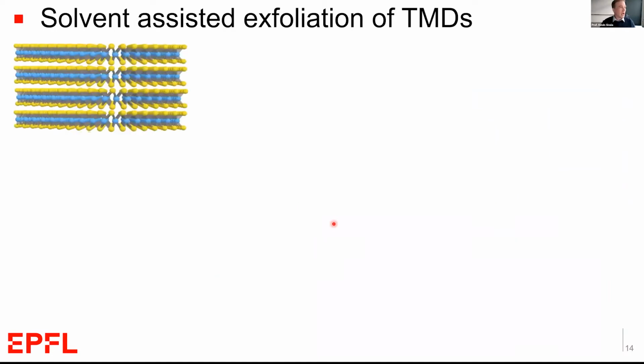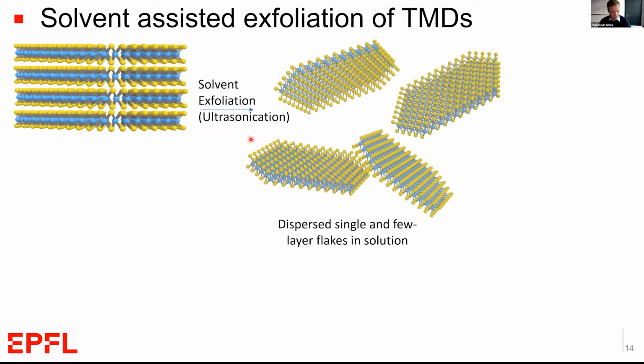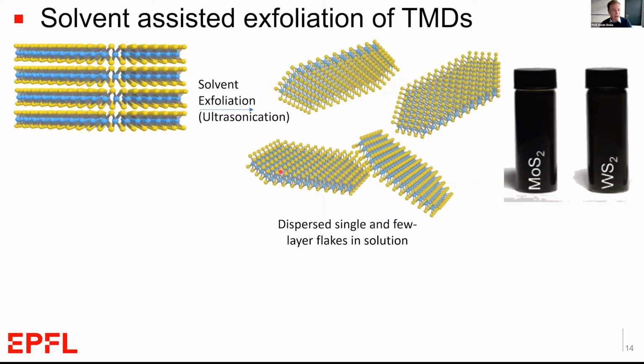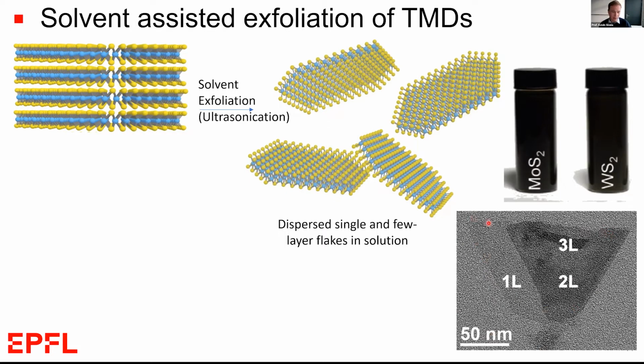Well, John Coleman's group in Ireland a few years ago developed a solvent-assisted exfoliation method where a simple bulk powder of these TMDs can be added to a solvent like NMP and then ultrasonicated using a tip sonicator to basically exfoliate these in solution, giving us dispersions of these nanoparticles or nanoflakes that look like this by transmission electron microscopy. They're not perfect. We don't have single monolayers, and maybe we don't have nice shapes, but nevertheless, they're nicely dispersed. So we can think about trying to coat these on a large substrate to make photoelectrodes for our water splitting reaction.